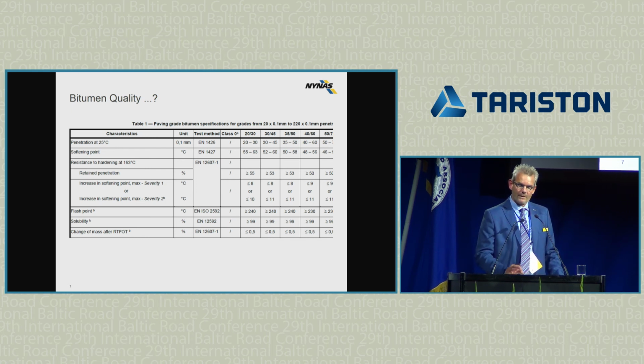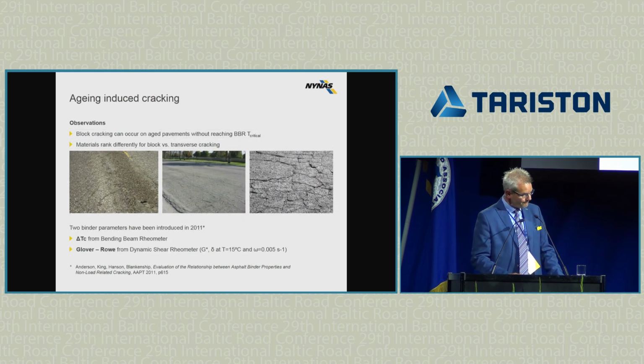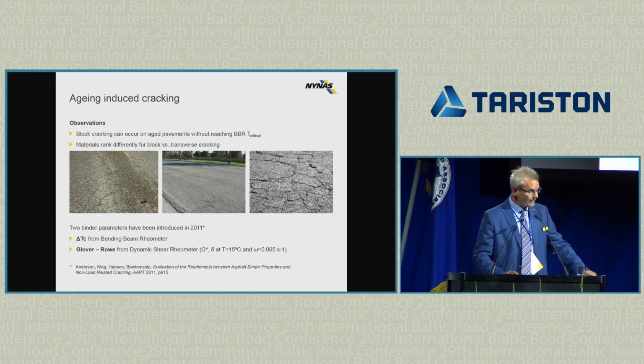We know that the bitumen has to last longer, so we have to look at long-term aging. And recent research from outside of Europe has shown that there are some failure phenomena that occur on roads, cracking-type phenomena, that are not directly related to temperature or traffic, but are more related to the aging of the asphalt surface and consequently the aging of the bitumen surface.